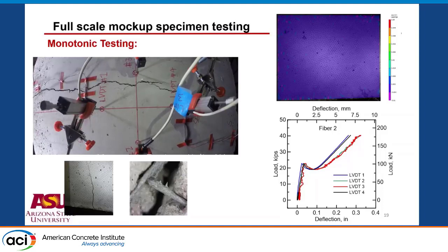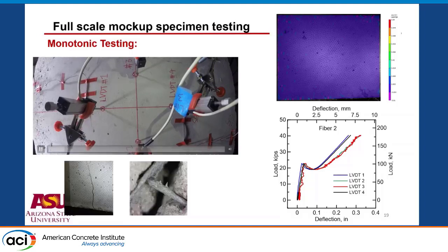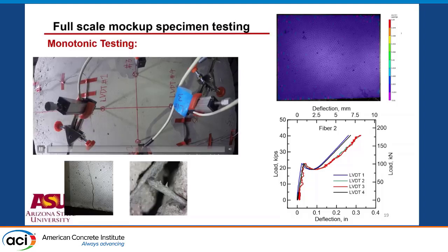So as the beam is deflecting. No graduate students were harmed in this test. We use the GoPro underneath the specimen. You can afford to lose a $200 or $300 camera, but safety is number one when it comes to the testing. At the same time, what you can also do is look at how the crack evolves and forms. And we have developed procedures for detection of crack initiation and growth within a flexural sample.